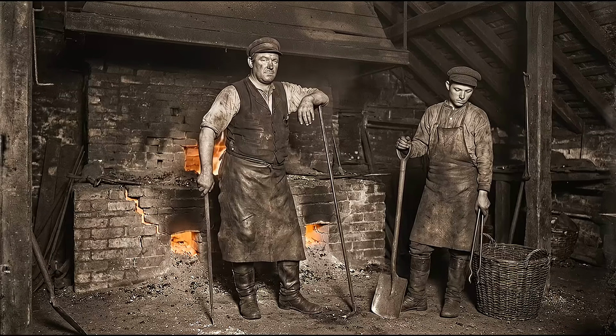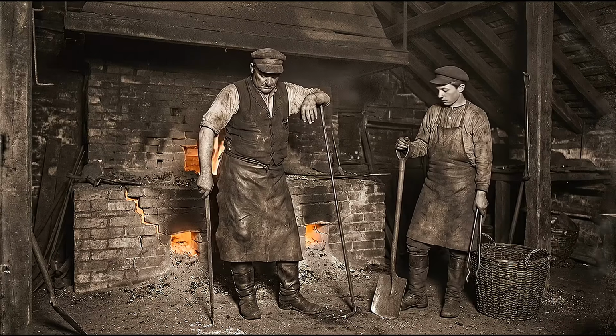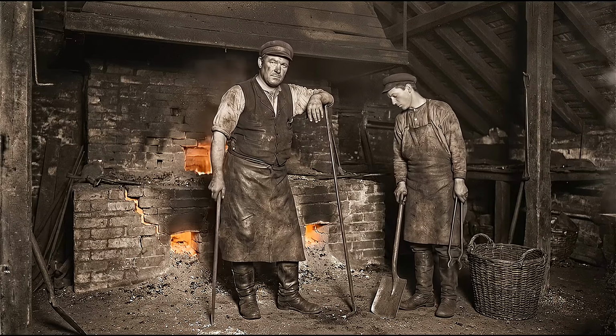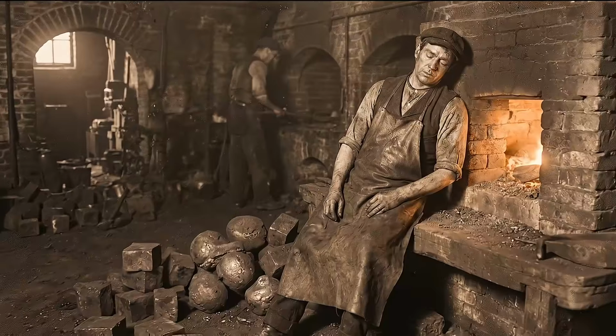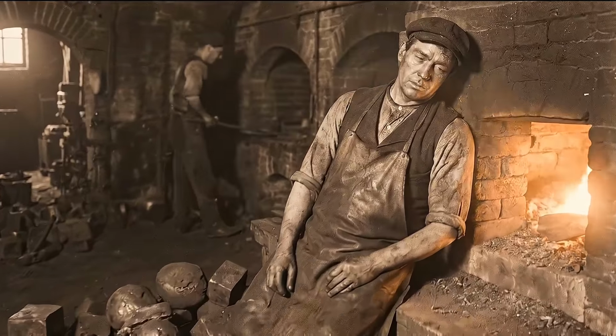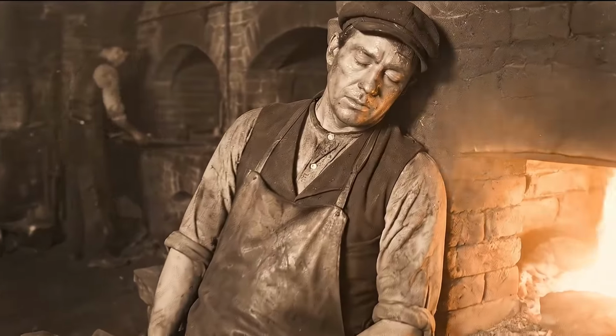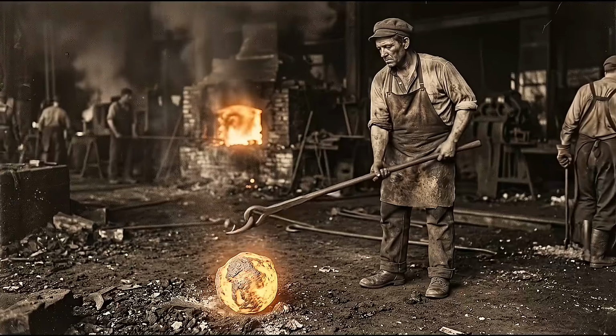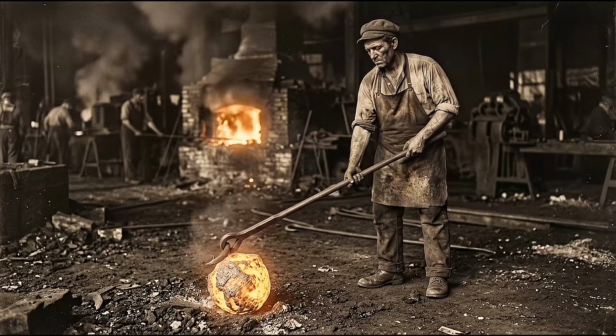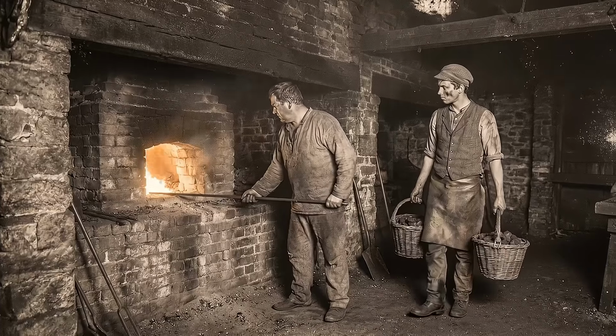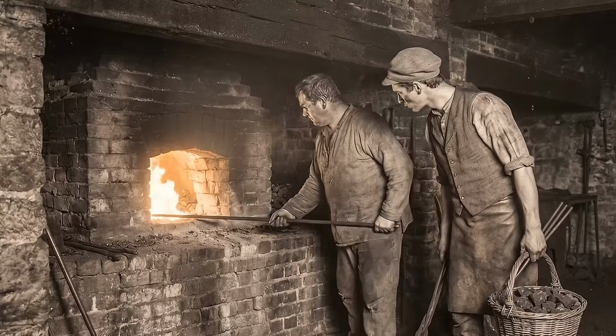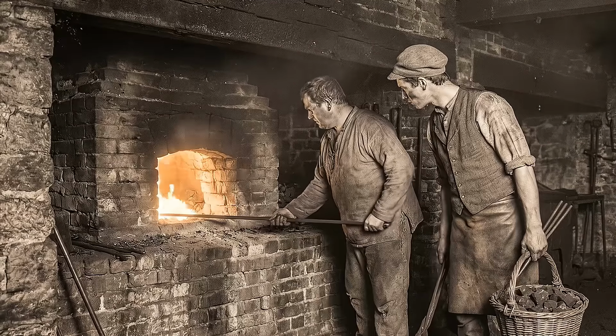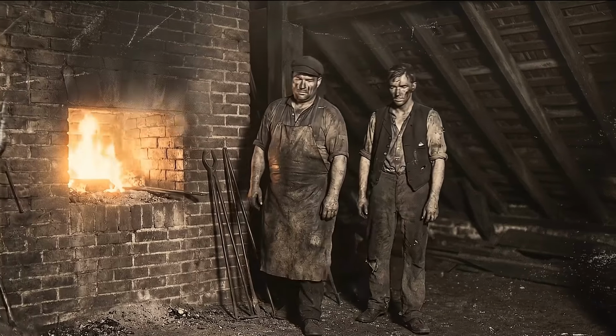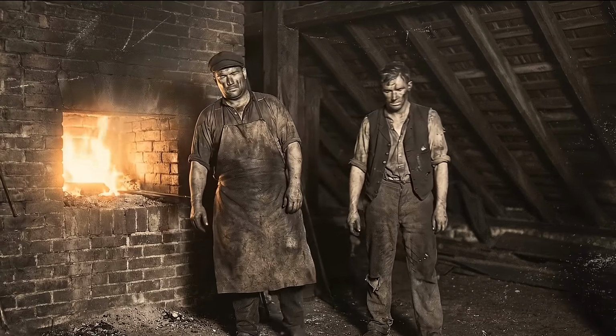A puddler and his helper could run 5 or 6 of these cycles in a single 12-hour shift. That means a puddler was pulling somewhere around 2,000 pounds of iron out of the furnace every working day. By hand, one 80-pound ball at a time. His helper, called an underhand, did the loading and kept the furnace fed with coal and managed the tools. The two of them worked as a team, and both of them paid for it with their health.